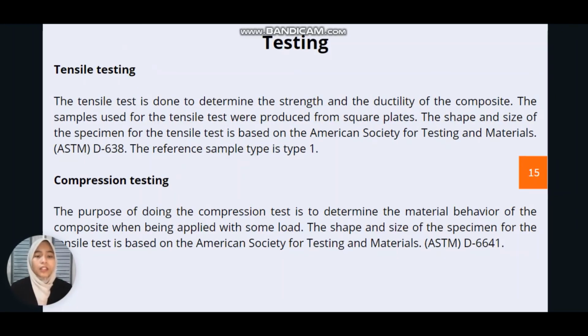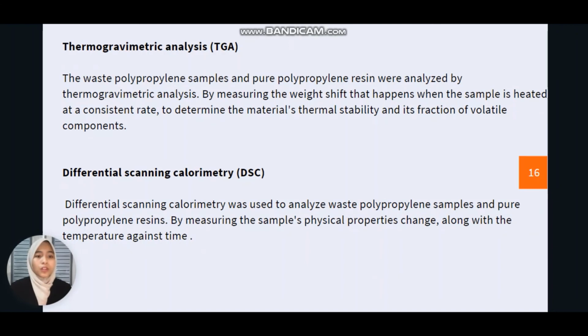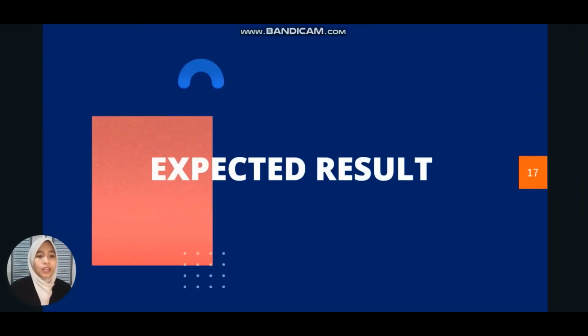So the testing that we made for this composite is tensile testing and compression testing. For the tensile testing, we use ASTM D638 as the reference for the shape and size of the specimen, while for the compression testing, we use ASTM D6641 for preparing the specimen in shape and size. And then we also do thermogravimetric analysis, TGA and DSC, on this specimen. For the TGA and DSC, we will analyze the recycled polypropylene and also the pure resin. So next, the expected result.